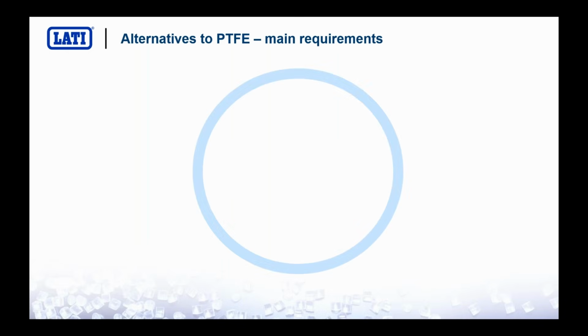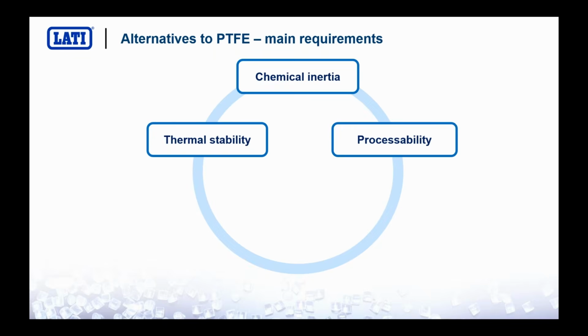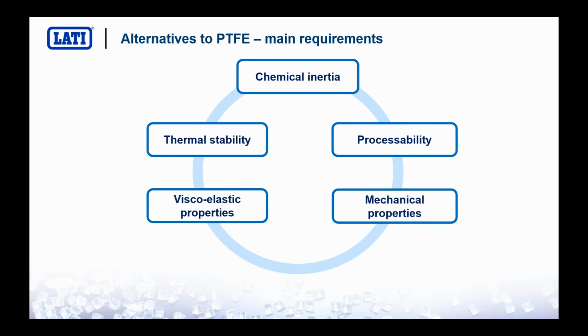So to be a good alternative to PTFE, what are the main requirements? For sure, the high chemical inertia, in order to not lower the chemical inertia of the base polymer. Thermal stability, for sure. A good processability, because it's important also to guarantee a good moldability of the final compounds, with good viscoelastic properties. Not compromising too much the mechanical properties, for sure, but probably the most important thing is an eye to the price.